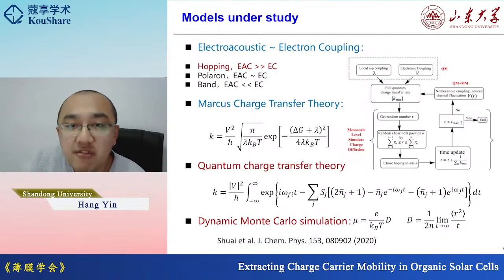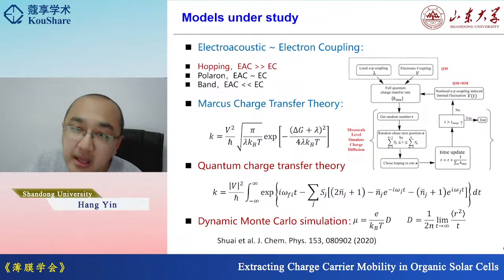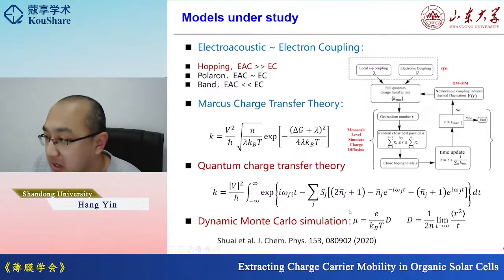To investigate the behavior of electron transport in organic solar cells, we need to compare the effects of the electron-phonon and electron-electron coupling. It means if they are comparable, the polaron model should be dominant. And if we do not need to consider the electron-electron coupling effect, then we can use the hopping model. And of course, very few reports so far talk about band transport in organic semiconductors. For theories, I think the Marcus theory is very useful, as well as the quantum charge transfer theory, and the dynamic Monte Carlo simulation is also a very useful technique.